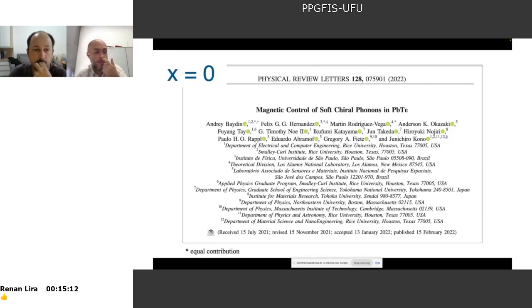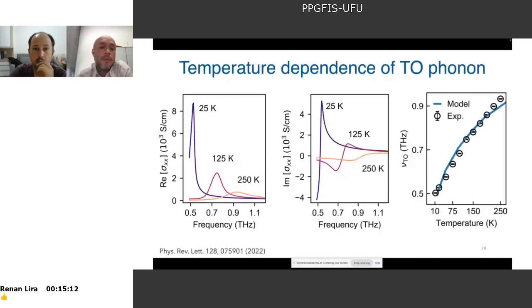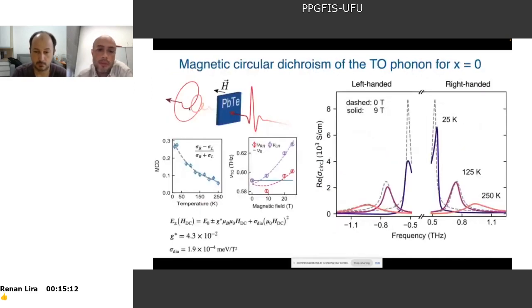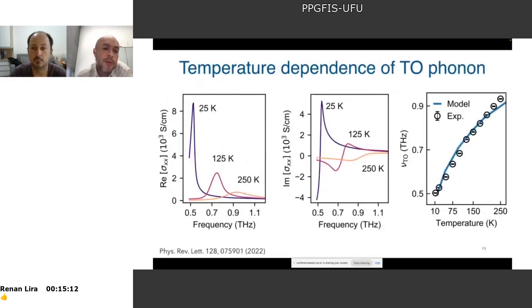Okay, so let's return here to the chiral phonons. First, I want to show you the situation when x equals 0, meaning lead telluride, and we published this PRL that we call magnetic control of soft chiral phonons. As a function of temperature of the TO phonon, we can see here the real part of conductivity, and we see that with decreasing temperature, the phonon peak, like in this example that I show you, moves to lower frequency. From almost room temperature to 25 K, the phonon becomes narrower, but also, more important for our application, it moves to lower frequency.